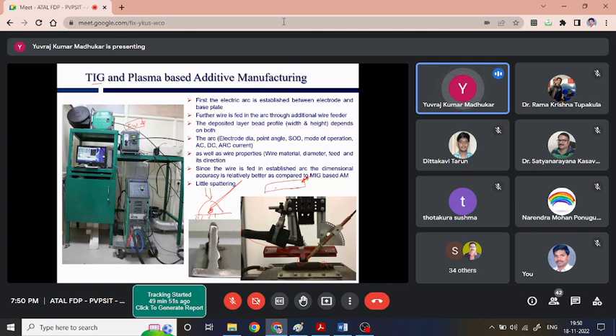If that happens, every time we have to manually cut this wire. So whenever we are buying a wire feeder, we have to ensure it has the retracting feature built in. Otherwise, we have to cut the wire manually every time, which is not possible when we are dealing with complex geometry deposition. So we have to make sure the wire is pulled back first before the arc is triggered. At the same time, while we are starting the deposition, the arc must stabilize between the electrode and the workpiece first. Only after that should the wire start feeding. So this push-pull mechanism must be enabled in the wire feeder.